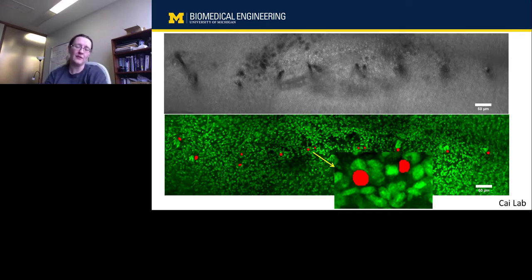And so while it's really hard to slice a normal size probe, because you're either going to break your blade or it's going to move the tissue as you break it, it's really hard to leave that in there. And people usually pull the electrode out, and then they find it based on the scar. For carbon fibers, we can just leave them in. And as we slice, they appear as little black dots. What you're looking at there is a bright field image from the microscope with a lot of black dots.